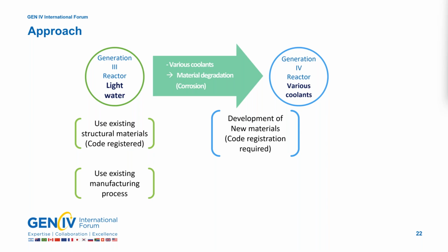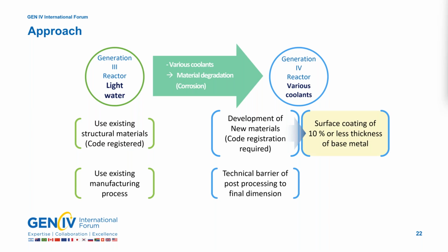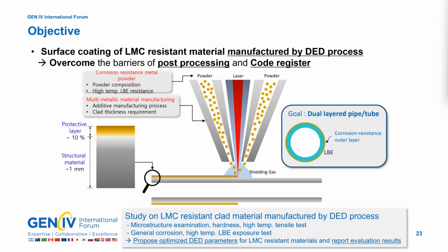However, to overcome the technical barriers related to the code registration and post-processing of the materials to their final dimensions, it is necessary to employ surface coating of 10% or less thickness of the base metal and optimize the parameters of the DED process to enable a thin coated layer. Therefore, the objective of this study is to examine LMC resistant clad materials manufactured by the DED process, propose optimized DED parameters, and report the evaluation results.